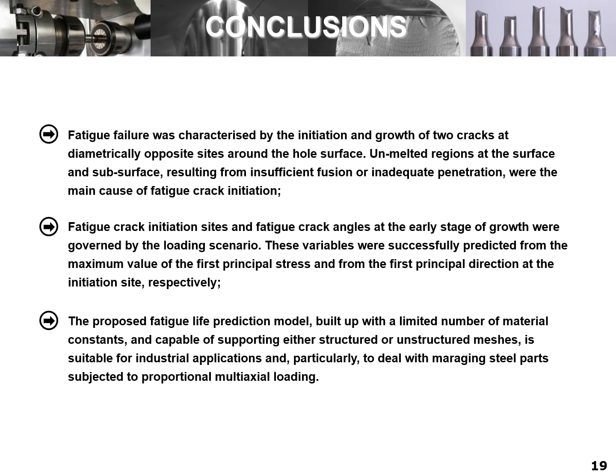Finally, some concluding remarks. 1. Fatigue failure was characterized by the initiation and growth of 2 cracks at diametrically opposite sites around the hole surface. Unmelted regions at the surface and subsurface resulting from insufficient fusion or inadequate penetration were the main cause of fatigue crack initiation. 2. Fatigue crack initiation sites and fatigue crack angles at the early stage of growth were governed by the loading scenario. These variables were successfully predicted from the maximum value of the first principal stress and from the first principal direction at the initiation site, respectively.